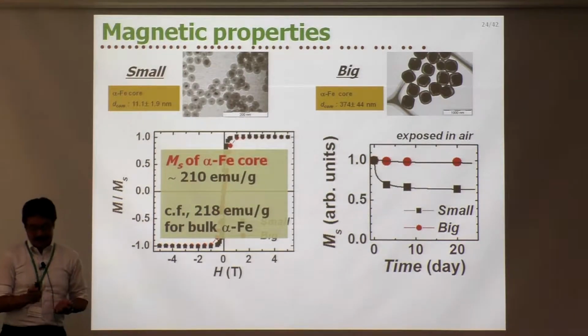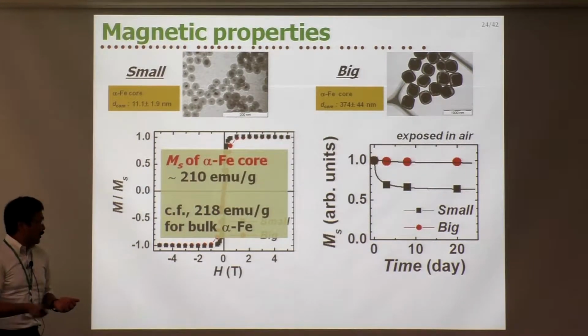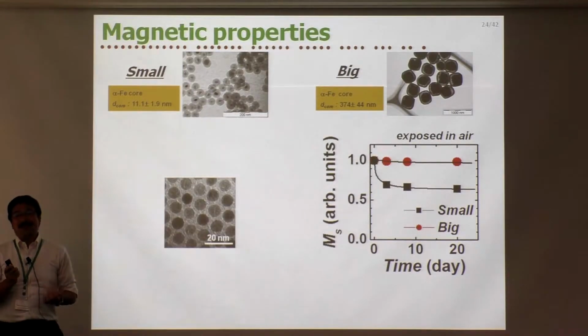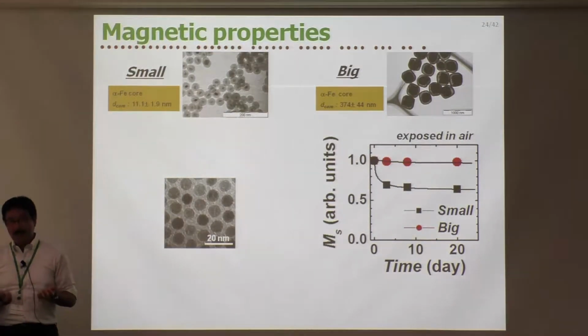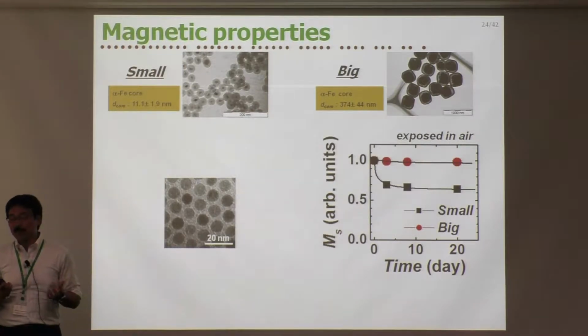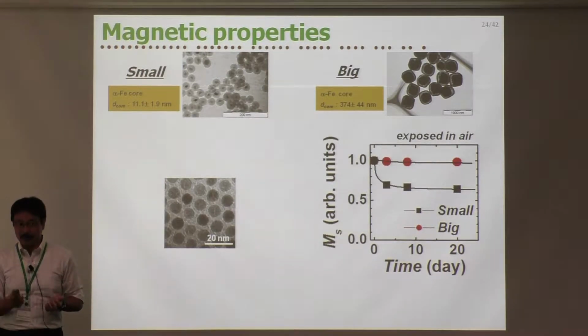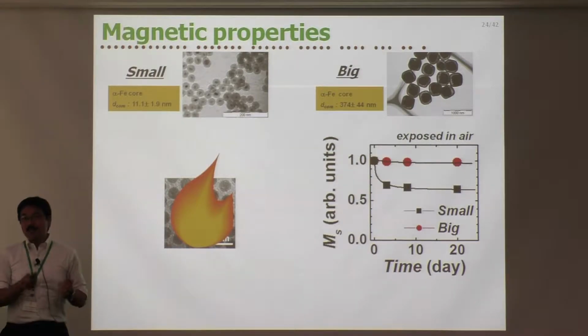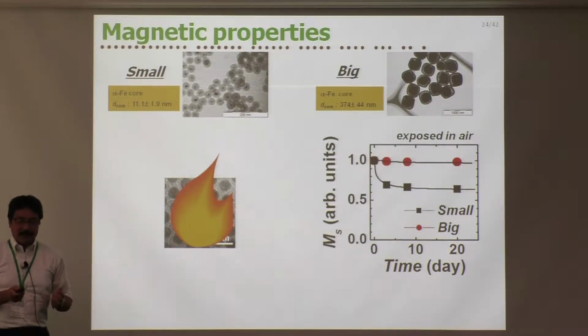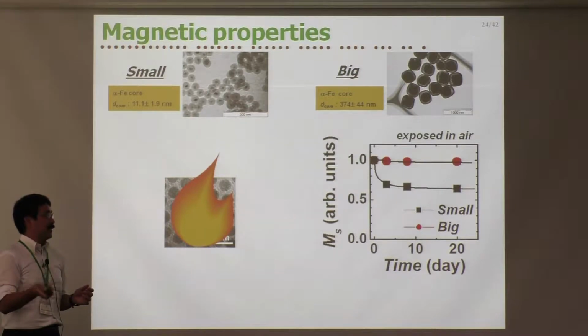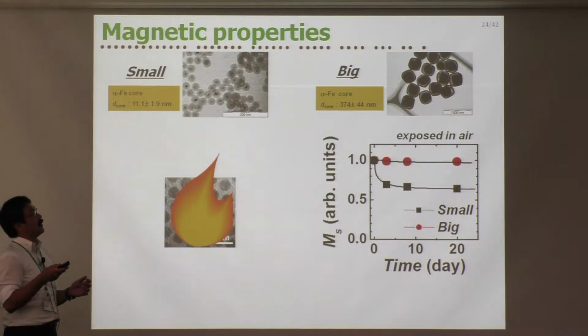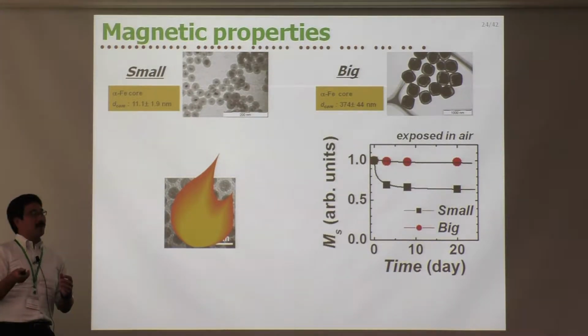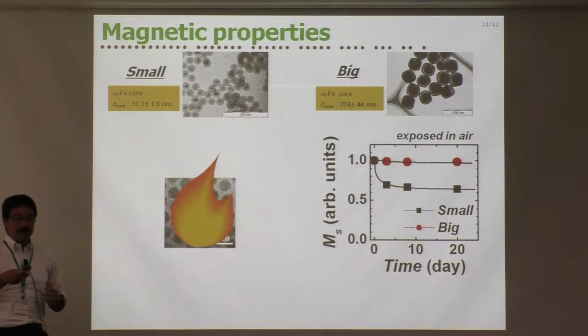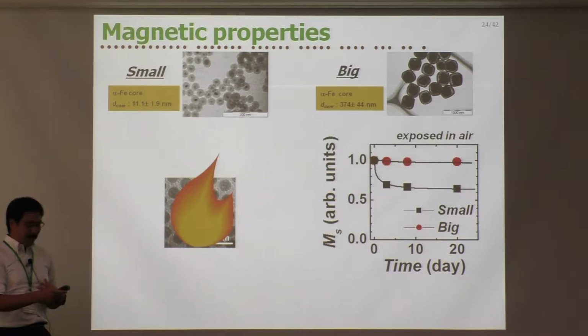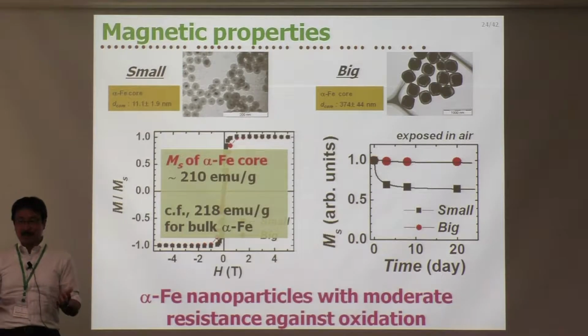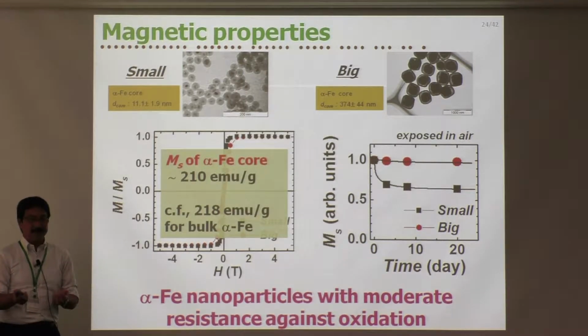I agree, but please remember: if we expose a bare, uncoated iron nanoparticle to air, it will immediately burn. So keeping this in mind, allow me to say our nanoparticle has a moderate resistance against oxidization.